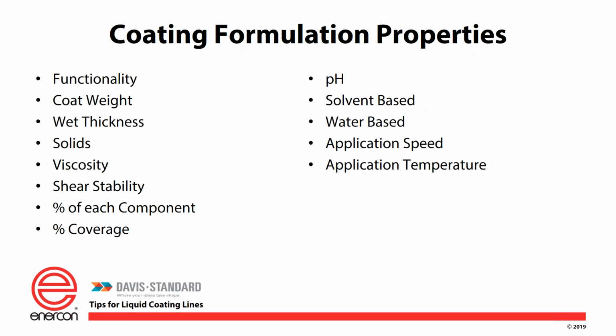Whereas if I'm using a solvent-based adhesive, some of your solvents are much less in weight. When I say a 1 for a density, that's 8 pounds to a gallon, 8.3, where adhesives are about 9.5 pounds. Some of your solvents can be as low as 6 to 7 or 8 pounds to the gallon. So density has a factor in that. It tells us what these wet film thicknesses are.